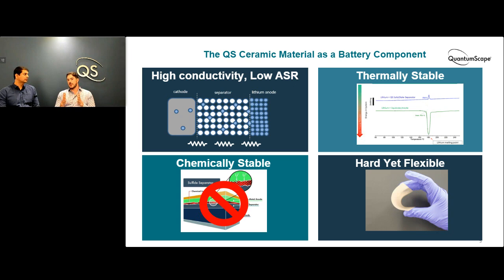The other thing that you get for free with ceramics is thermal stability. Ceramics are all high-temperature materials. When you heat them up, they don't do anything until they get very, very hot near their melting point, and that's usually over 1,000 degrees. And you can compare that to a lithium ion battery today, which has a polymeric separator that will melt at a few hundred degrees, and then you get catastrophic failure of the device. That won't happen at a few hundred degrees with a ceramic separator. It's very stable over a broad temperature range.